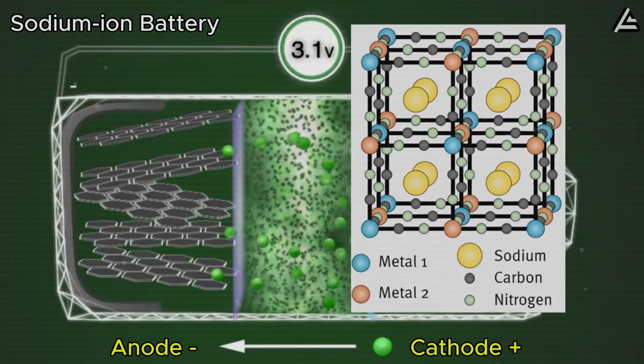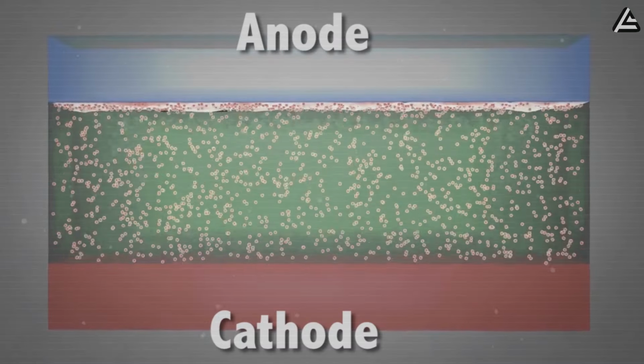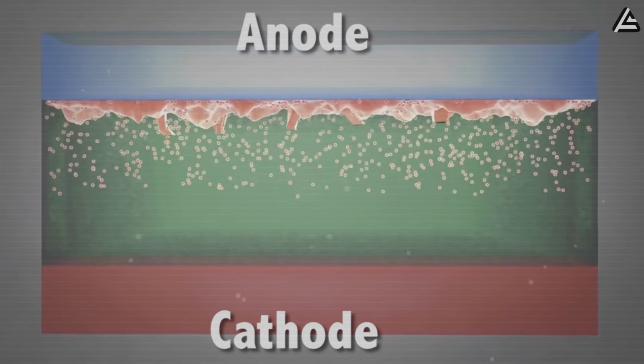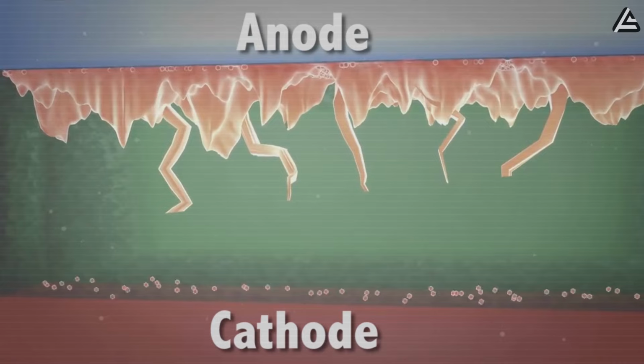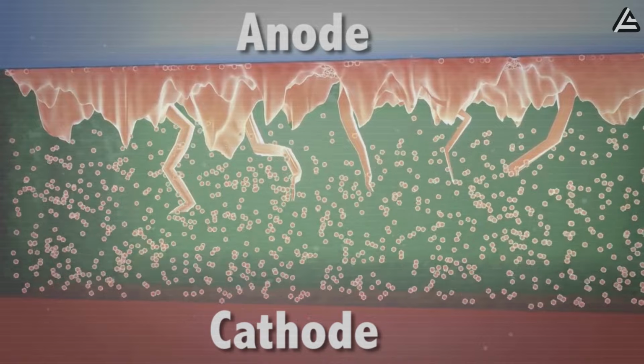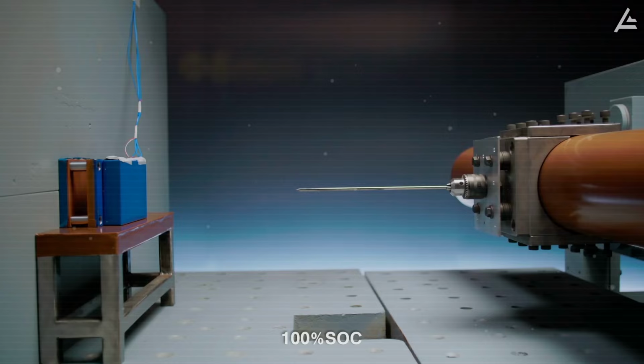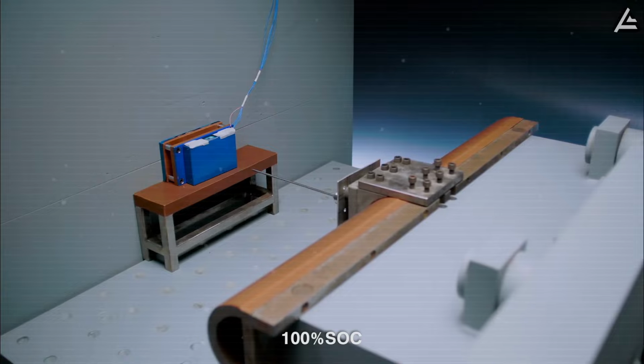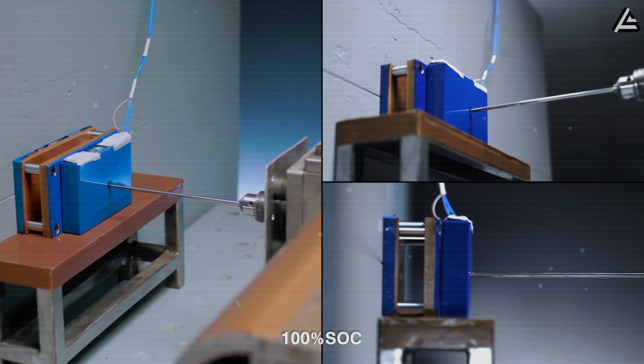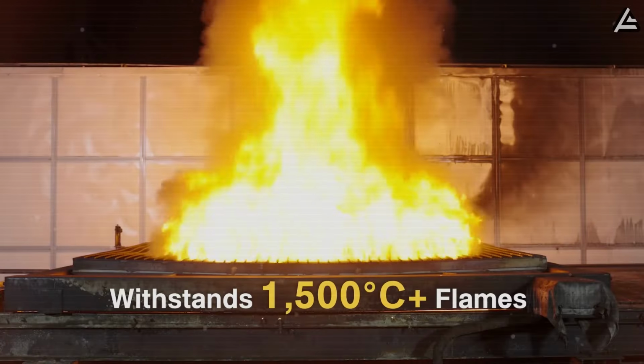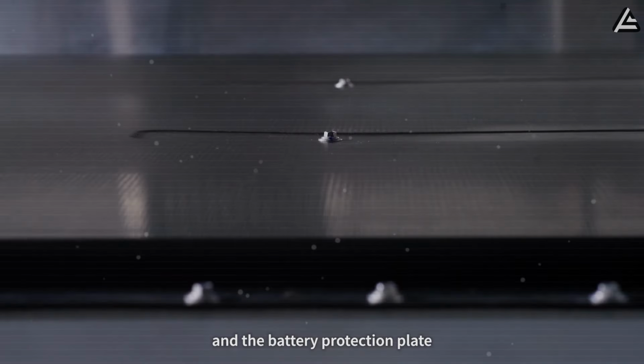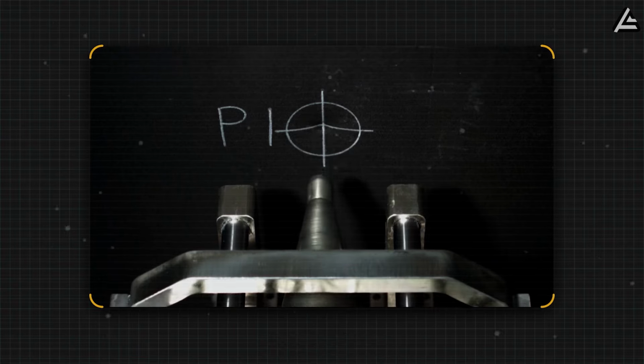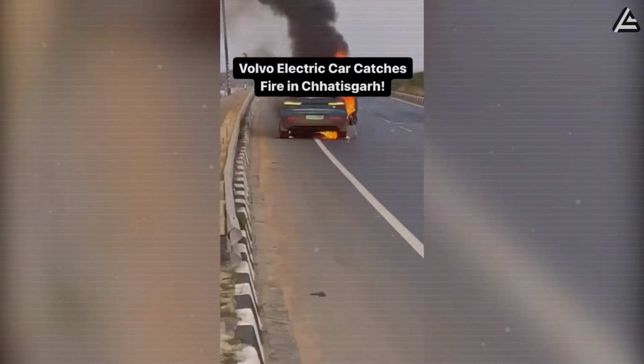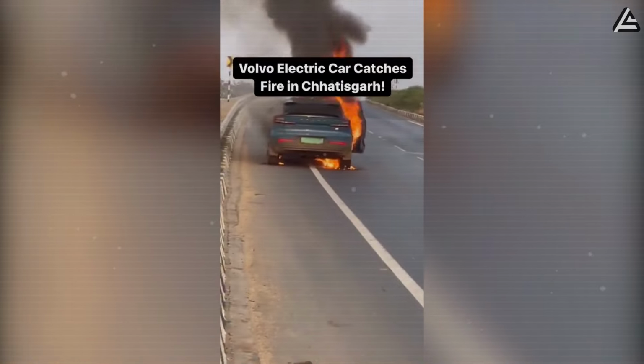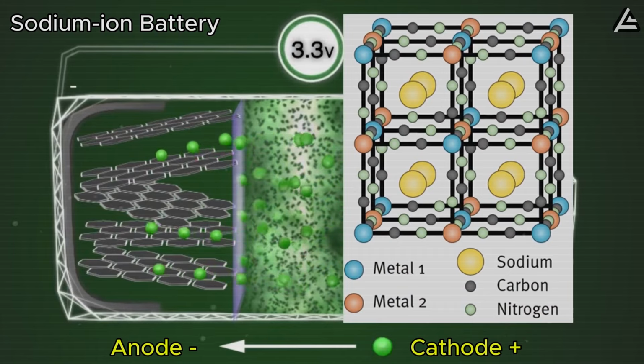Sodium-ion batteries are chemically modest. Sodium doesn't form the sharp metallic dendrites that plague lithium, those microscopic needles that pierce separators and trigger short circuits. In 2024, CATL ran a brutal series of tests: nail punctures, open flames, and even direct crushing. And the sodium cells didn't ignite once. A lithium pack under the same abuse burns within seconds.